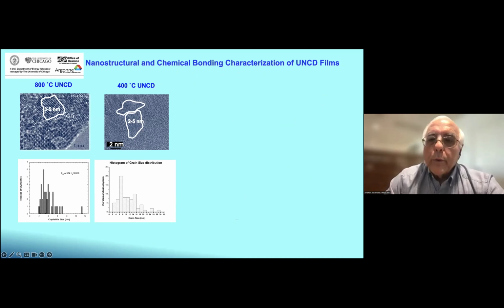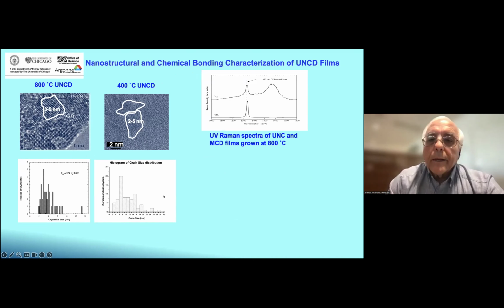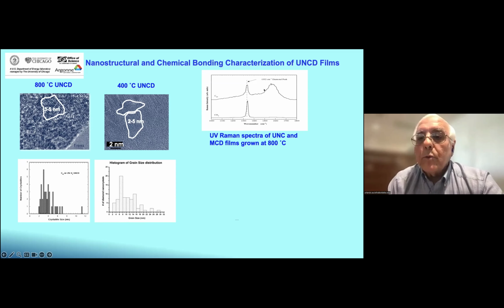Now, when we were doing a UV Raman spectroscopy, and when you do Raman spectroscopy of a gem of diamond, the characteristic peak is this one at 1332 centimeter minus 1. We were seeing that peak, but also we were seeing this broad peak that correspond to sp2 carbon bonding. And so people started saying, well, you also have graphitic impurity. And we said, those are bonds of carbon in the grain boundary.